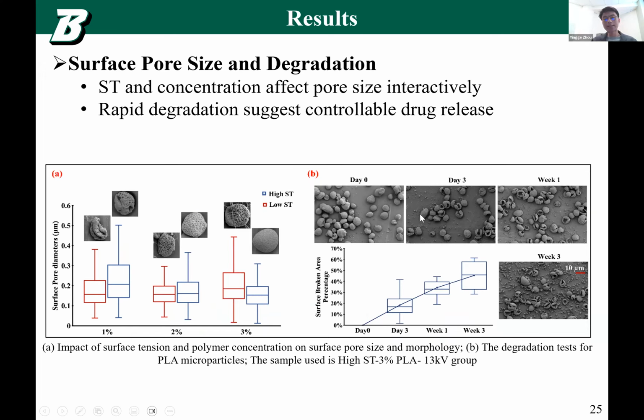And we also test the degradation. If you remember, we still need the polymers to be degraded, right? If they have a core shell size, if they have surface pores, would it be easier to degrade, right? This is day 0, day 3, week 1, and week 3. As you can see, they're broken up, which means it's good. They're releasing the drugs in the core, right?